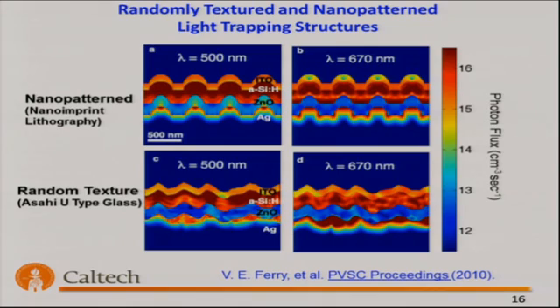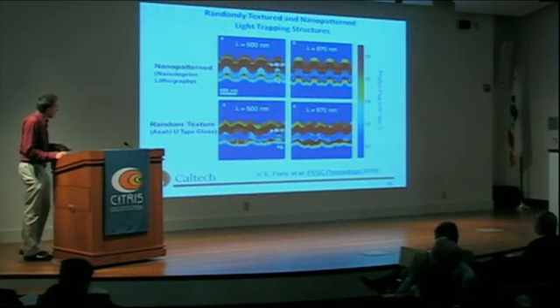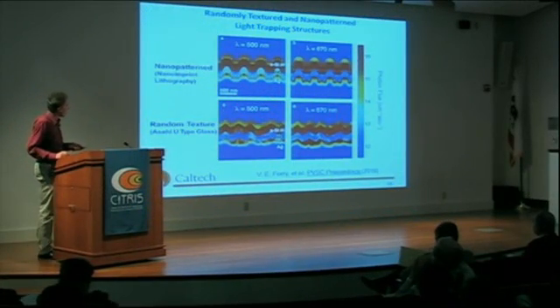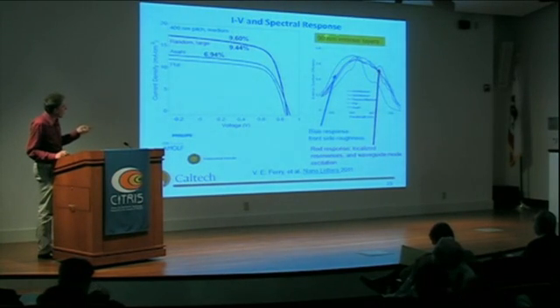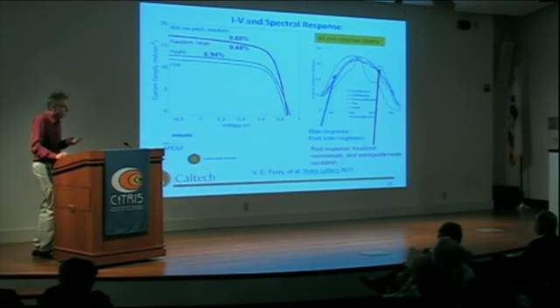You find that these sharp asperities here give rise to localized resonant modes in the metal, loss in the metal. A more gradually curved structure, which you can achieve by nanoimprint lithography, now provides very strong scattering, but less parasitic absorption in the metal, and enhances the photocurrent of the thin film amorphous silicon solar cell considerably. In fact, this thickness here, 90 nanometers, is 1/3 the thickness of a conventional amorphous silicon solar cell, and achieves near record. The world record for a single junction cell is around 10.2%, and the highest we achieved was 9.6.